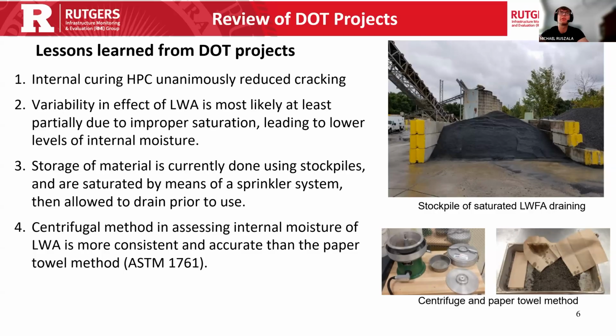So, a pile of material saturated by a sprinkler system over time. And then before use, it's allowed to drain prior and excess water to run off. Then you need to find what degree of absorption this material is carrying. That's done by using ASTM C1761, and you can choose either the centrifuge method or the paper towel method. We extensively tested both.